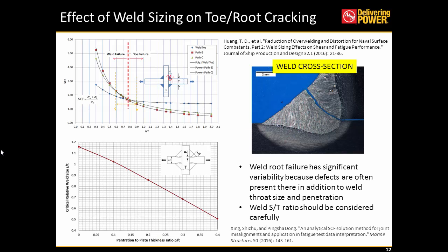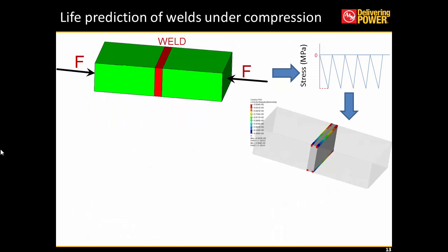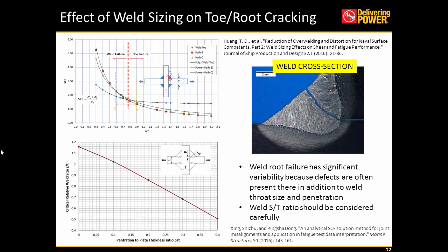So the first case we are talking about is the effect of weld sizing. We look at the plot on the top left-hand side. It's not very clear. The x-axis represents the s by t ratio, where s stands for the weld leg size and t stands for the plate thickness. And the y-axis is the stress concentration factor. So what we observe is that